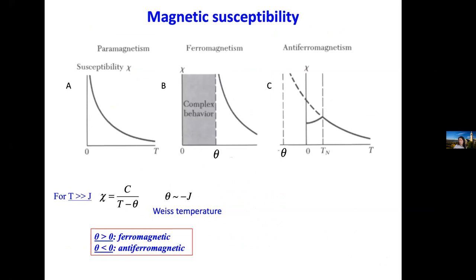The ground and the low energy excited states of the Mott states are determined by interactions between the localized magnetic moments that survive charge localization. To gain insight into the magnetic interactions, we measure the magnetic susceptibility as a function of temperature and perform Curie-Weiss analysis. We do the measurement of susceptibility at high temperature and try to extrapolate to get the nature of interaction at low temperature.